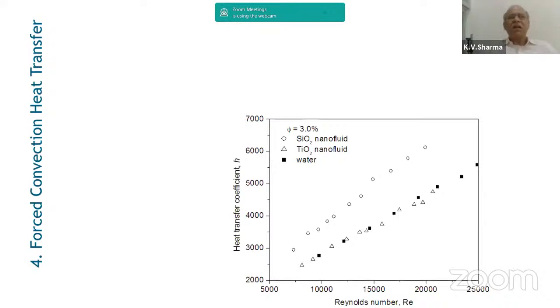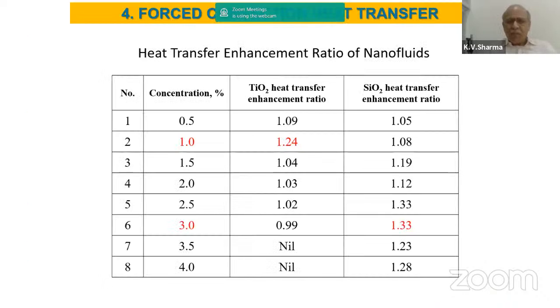So it is not always advantageous to go on adding nanoparticles or increasing the concentration just like that. We have to have clarity as to why we are adding, when we should add, and up to what conditions this heat transfer gets enhanced. Similarly, for TiO2, we see that at 1%, it gets a maximum enhancement of about 24%, whereas SiO2 at 3% gives a maximum enhancement of 33%.